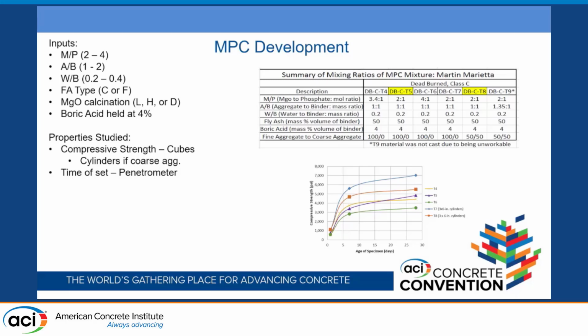And so we started out, we did light burn, we did the hard burn, and we quickly learned that dead burn gave us the best strengths and also the best set times. So the burn is all associated with the temp at which it's calcined in a furnace. So dead burn, I believe, is 1200 C, maybe more than that. And so we varied them. We quickly settled on a dead burn Class C, and that's just trial number 8.